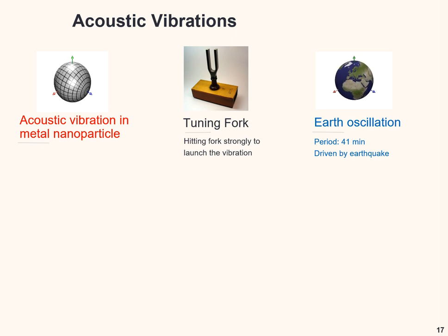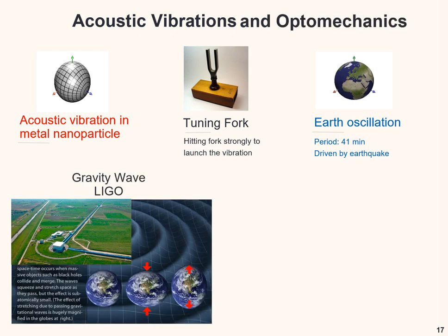Our planet has these acoustic vibrations, driven by earthquakes. But what is the hammer to launch acoustic vibrations in a nanoparticle? We cannot use a hammer to hit the particle, as it would destroy it. The method I'm talking about is using an ultrafast laser. Remember, after electron-phonon coupling, we inject a lot of energy into the nanoparticle in a very short amount of time. The nanoparticle becomes hot very rapidly and expands very rapidly. That's the hammer. Ultrafast is our hammer to launch this acoustic vibration.